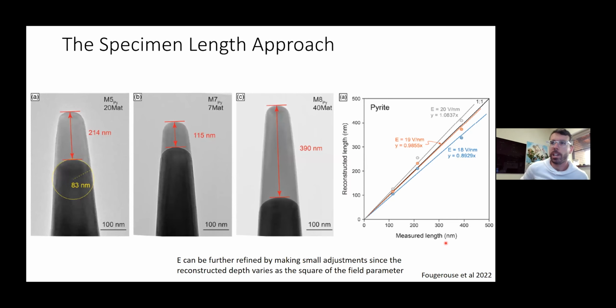But once we overlay the images, we can do it for several tips, and we ran for several different durations of between 7 to 40 million ions. Then, with the different iterative field values, we can see which value best matches the measured length with the reconstructed length.